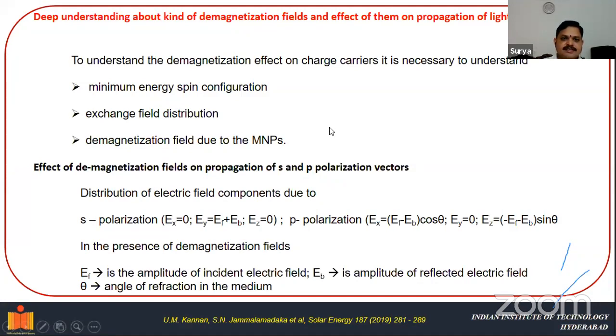The simulations give a deeper understanding about the demagnetization fields and the effect of them on the propagation of the light. Now we also try to do the simulations to understand the demagnetization effects on the charge carriers. What we must know is the minimum energy spin configuration and exchange field, how the exchange field is distributed within the device, and the demagnetization fields due to the magnetic nanoparticles. Okay. We also try to see the effect of demagnetization fields on the propagation of S and P polarization vectors.